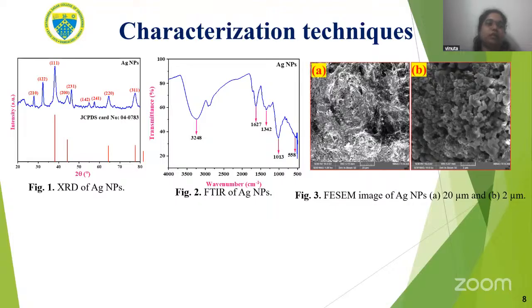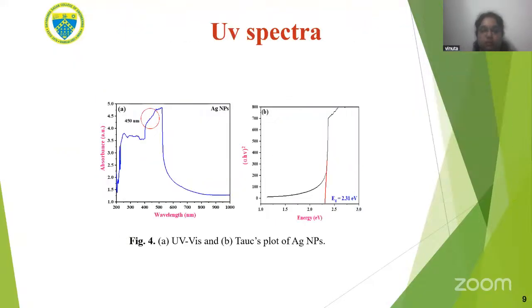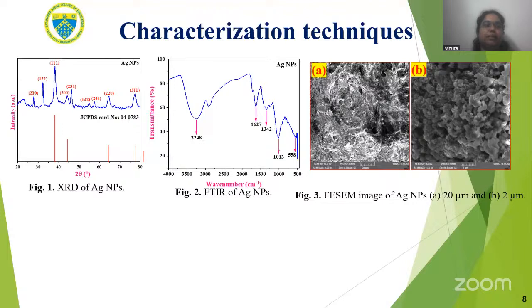Metal nanoparticles undergo stabilization, capping, and reduction due to the plant extract. The peak at 1342 corresponds to the OH bending. The peak at 3248 centimeter inverse corresponds to OH stretching, which is due to the presence of the aliphatic carboxylic acids. So these peaks were mostly attributed to the abundance of flavonoids and terpenoids present in the plant extracts.